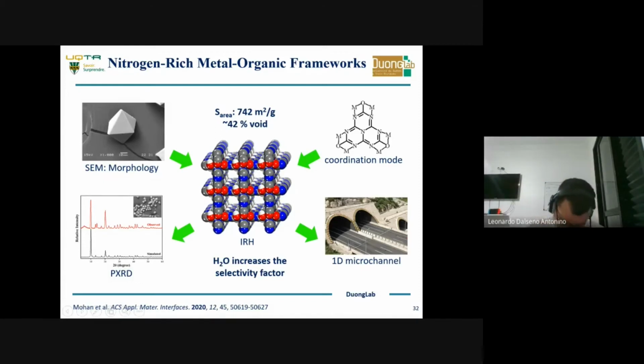Remember that single-crystal X-ray diffraction is only solving one crystal. But what happens with the thousands of other crystals? Are they having the same structure? You don't know. So what you can do is use powder X-ray diffraction to define if all the crystals have the same structure. You take the single-crystal X-ray data, simulate the powder X-ray pattern, and compare it with the experimental one. If you find that it's quite similar, then the chance that the thousands of other crystals have the same structure is high.